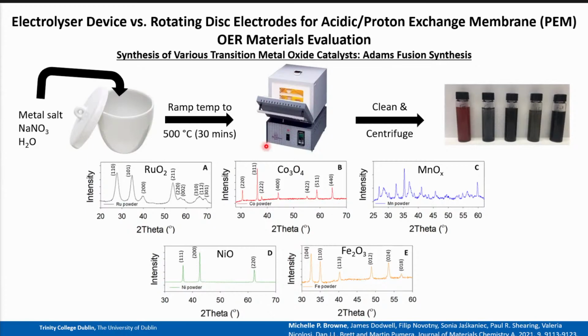So for most of the materials, we had an exact phase. But for the manganese metal salts, we had a mixed phase, but I can't stress enough, because this is not trying to find the best OER catalyst, it's trying to evaluate 2 different platforms. We didn't need an exact phase of our catalysts. We just needed the same material to be used in both different platforms.